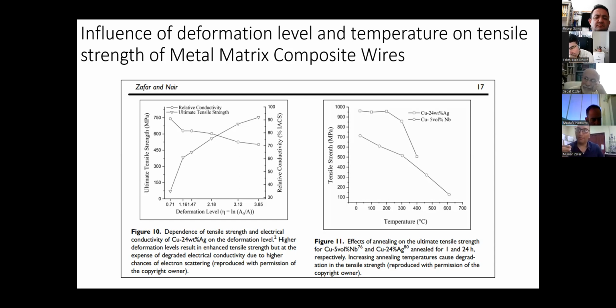It is a good thing to have a high hardness and a strength, normally they are connected, but the grains must be cohesive enough to transfer these loads to the next grain and then the next grain and the next grain when they are under mechanical loading. Then when you try to pull the wire, the first thing that happens is the breakage at the interface of the core of the wire. Yes. Okay. And then the core behaves independently and the sheath behaves independently. If you see the tensile behavior of the wire, it is only the sheath which is taking all the load. Yes, and it is understandable because a large fraction of the region is borided, and a very hard and brittle material, when it is subjected to tensile loading, eventually is going to have a transverse crack like a concrete, and nothing will happen after that.